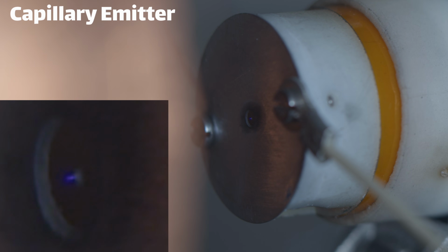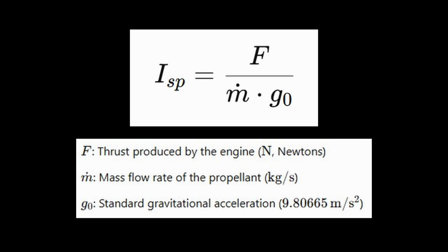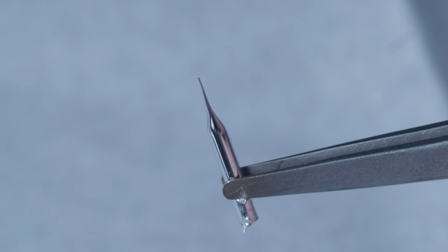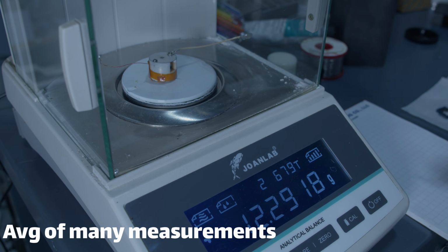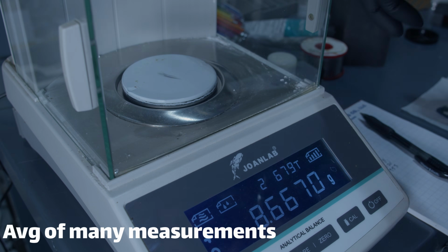But thrust is just one of the measures, and I was curious what the efficiency, the specific impulse, was. To do that, we need to measure the mass before and after a test fire so that we can calculate the mass flow rate. The spike unfortunately just doesn't really carry enough propellant to measure easily with my equipment, so I loaded up a capillary, massed it, and ran a test for 30 minutes. Afterwards, we can calculate the change in mass, and from that, the specific impulse.